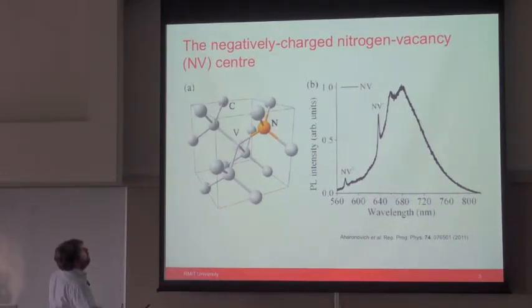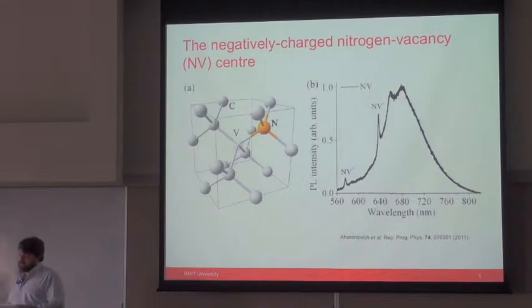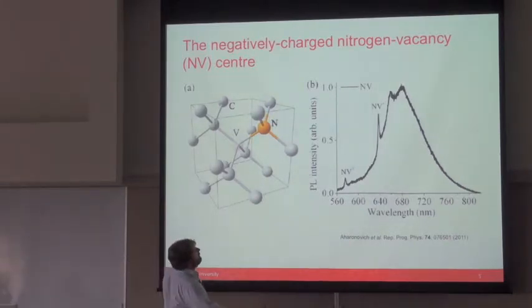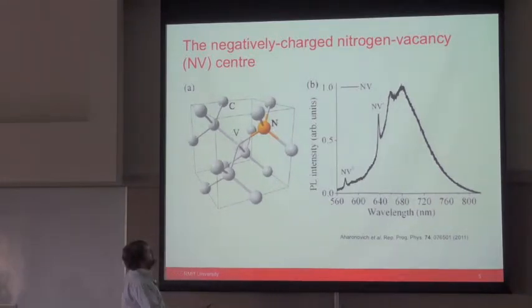It comes in 2 forms that are routinely seen, the NV0 and the negatively charged NV-. I'm not going to worry about the NV0, it's the NV- that we care about for its particular electronic properties. And so here this shows the fluorescent spectrum that you expect when you excite an NV center in the green, such as with this laser pointer, you'll see an emission here at 637 nanometers, which is the zero phonon line, and then this broad tail of emission.